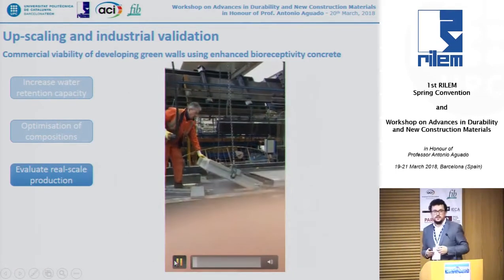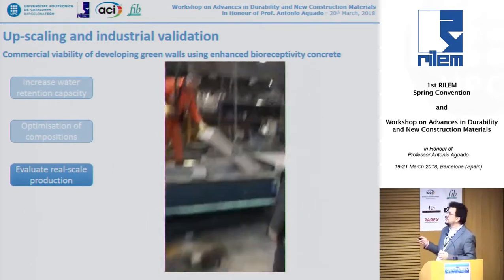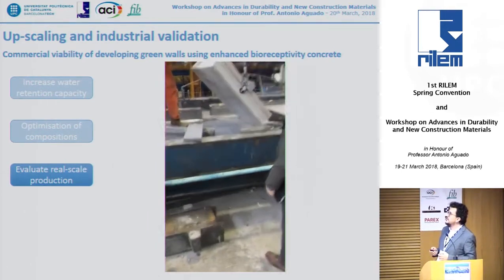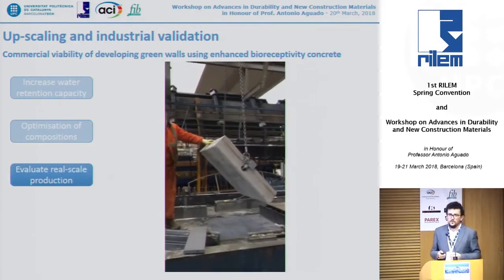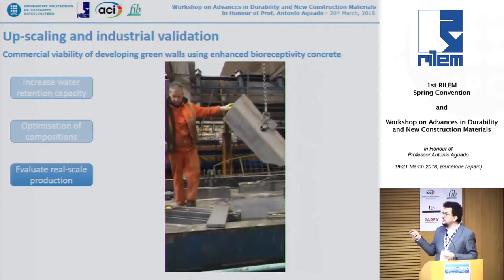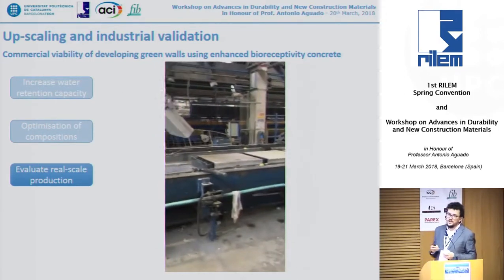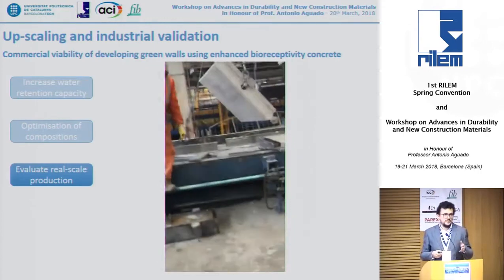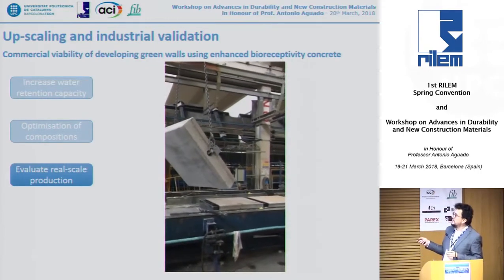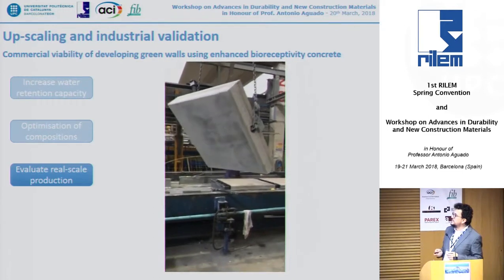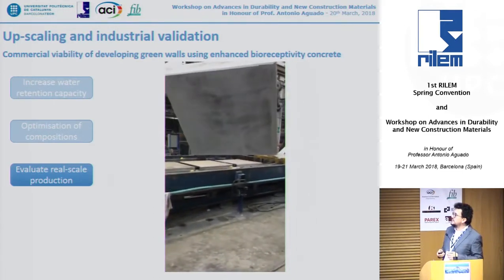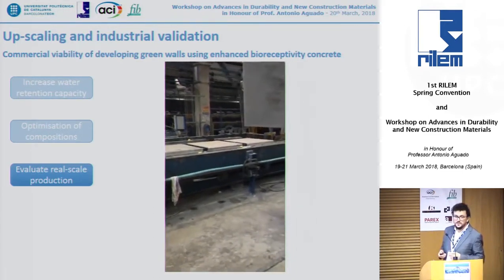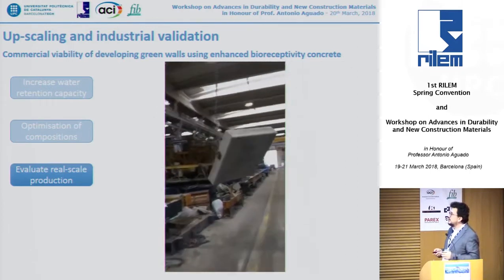This is just 24 hours after the production of the elements. We are having a compression resistance of the biological layer of around 8 to 10 MPa, but there is very good adherence between both of the elements. The movement of all the panels was really okay.